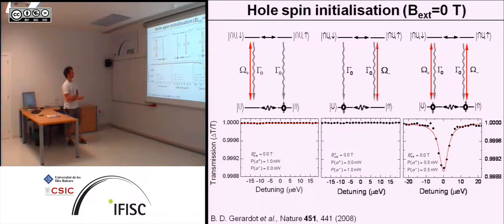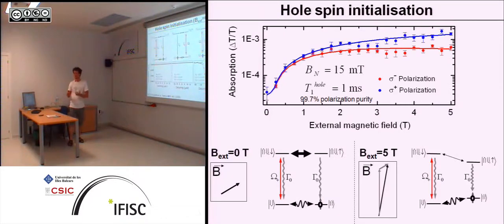And one thing to note here is this is all at zero field. So this addressing is only done by clean optical selection rules, so that already shows that the quantum dot really behaves at least to a high degree like an atom, or like an idealized atom in this case. And because the energies are completely degenerate, there's no energy selectivity. Okay, so how do we study this effect a bit more?